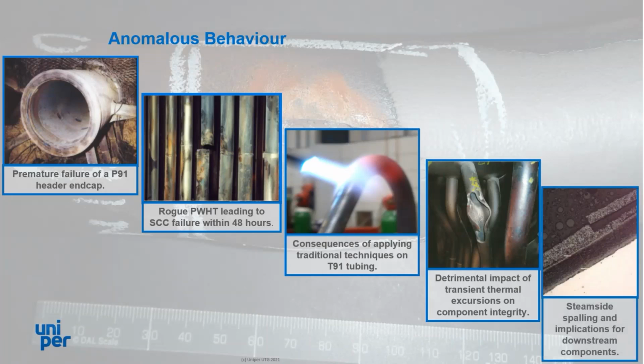In a presentation that I saw Jeff Henry give a number of years ago on US experience related to the spallation of steam side oxides on grade 91. Already well recognised on austenitic stainless steels, this has become more of a recognised issue on grade 91, not purely in the US, but there's also been a few examples noted in mainland Europe as well, with implications for downstream components more than necessarily the grade 91 component itself, resulting in erosion damage to valves, to bends in drains, strainers, as well as turbine blades.